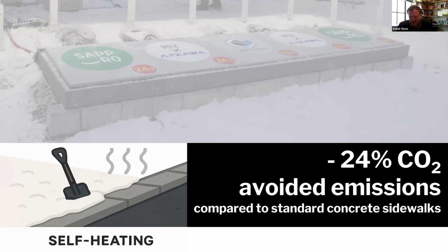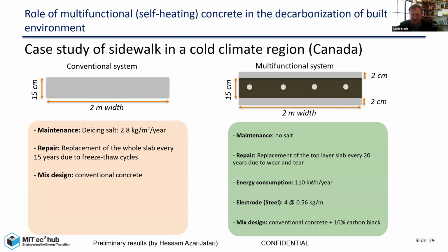And here is an important number that comes from our Hessam's work, where Hessam calculated the avoided emissions compared to standard concrete sidewalks. Here are some details of these calculations, where he considered a conventional system where you need maintenance, de-icing salts, and repair and replacement of the whole slab after every 15 years, and the mix design is conventional concrete, whereas this self-heating multifunctional system would not require salt and requires slab replacement every 20 years and energy consumption of about 110 kilowatt hours per year. The mix design is our carbon black, 10% carbon black in conventional concrete.